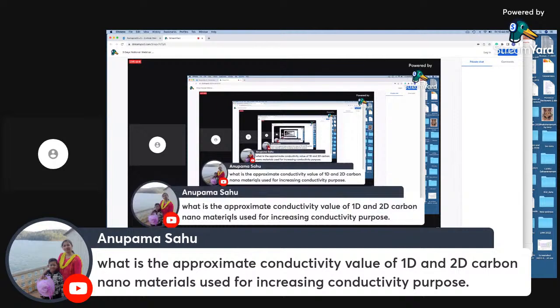Any other question? No, we have not checked with reference to the electrical conductivity. But normally what happens is that the two-dimensional graphene has been obtained mainly because of the use of graphite oxide. First synthesize a graphite oxide by acid treatment and then reduce it to graphene using hydrogen. So some of these oxygen functional groups will be present. That will actually reduce the electrical conductivity.